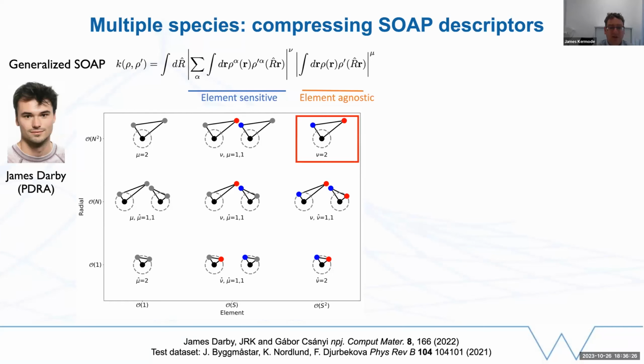So the traditional SOAP has nu equals 2 and mu is 0. It only has the element sensitive part, and that leads to a descriptor which scales quadratically, both with the number of chemical species, S, and with the size of the radial basis set, N. And by playing with these numbers, we can reduce that. So we can come down here to reduce to linear cost, or actually we can also compress in the radial direction, and that's represented in this picture by projecting onto the unit sphere. So taking one of our neighbors, keeping both its chemical species information and its distance information, and for the other one, bringing it in so it lies on the unit sphere.